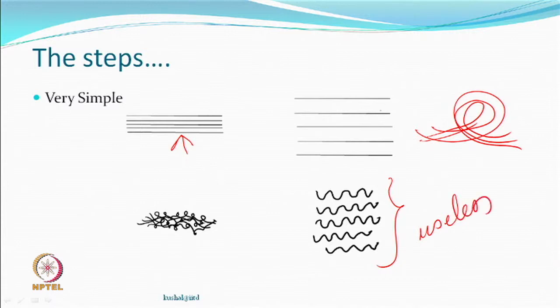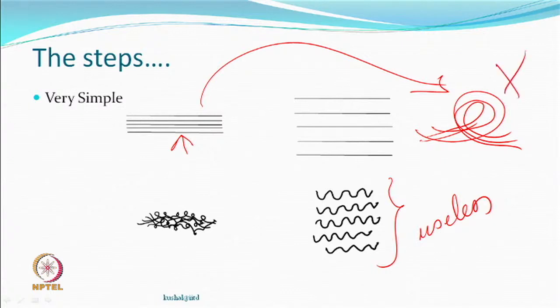If loops are there but have not been entangled, they can open again — without entanglement it is useless. You require entanglement where loops are projecting out, and some area within the yarn — not projecting out — is still holding the different filaments at positions more separate than otherwise they would have been. This is how you increase the bulk.